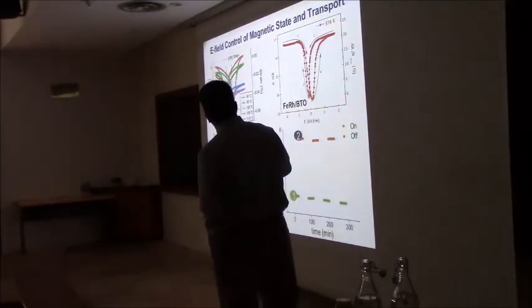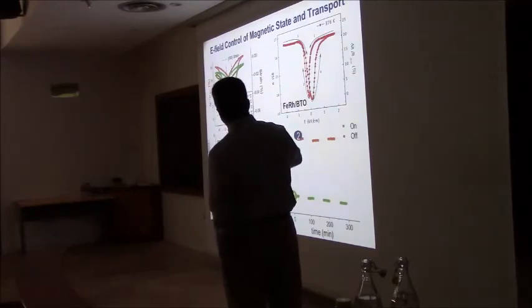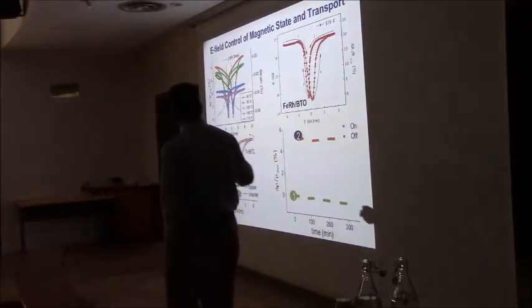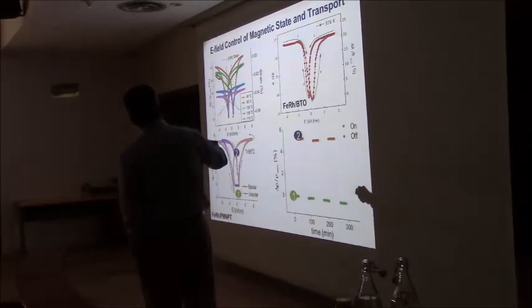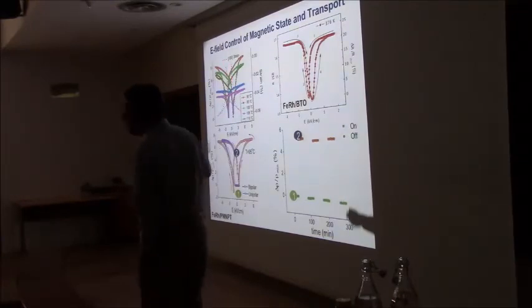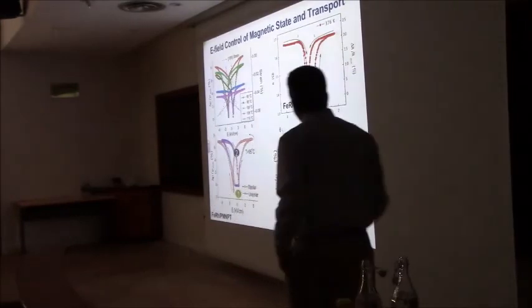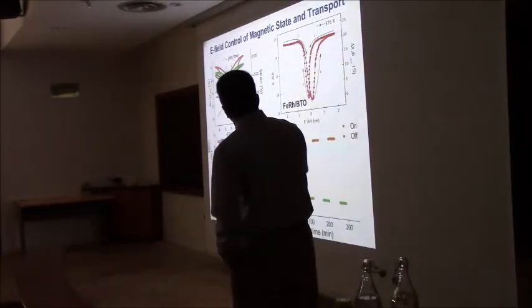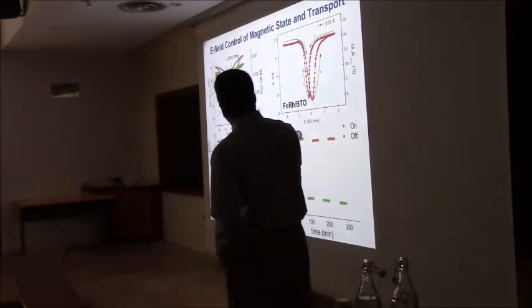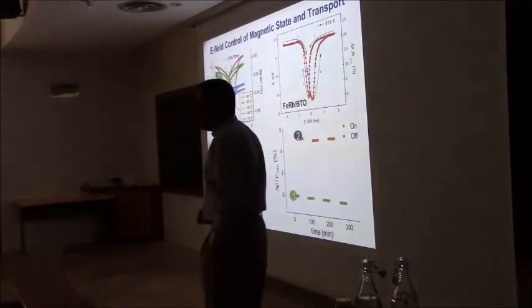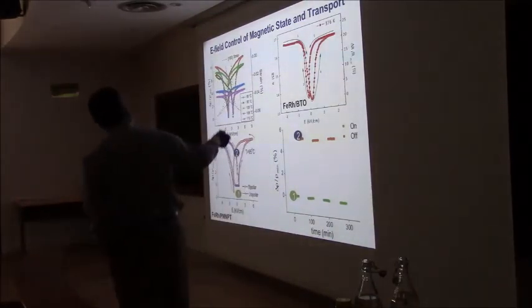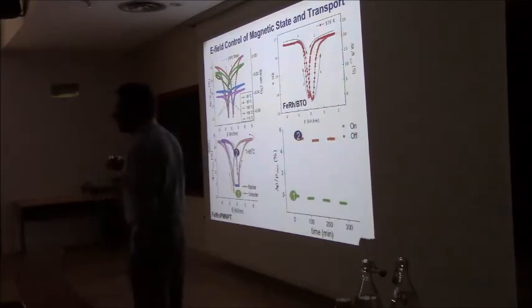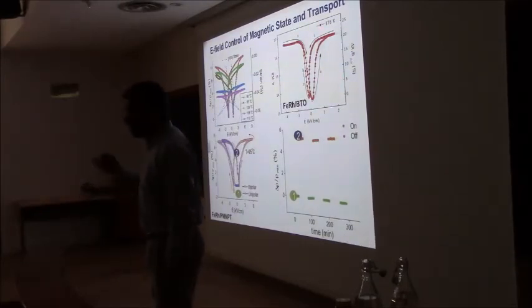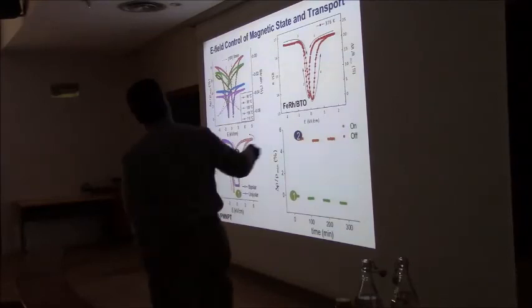What we find is that this is on a piezoelectric surface, the PMN-PT crystal, basically. When I switch it, you can see the dotted lines are basically the strain in the PMN-PT. You can see very large strain. That's a switching. It's about 2 to 3 kilovolts per centimeter as a switching field for the crystal. You could see very large changes in the resistance of this. It is quite possible, I'm going to show you more data here, to change the resistance of this material, this is a metal, by about 20%.